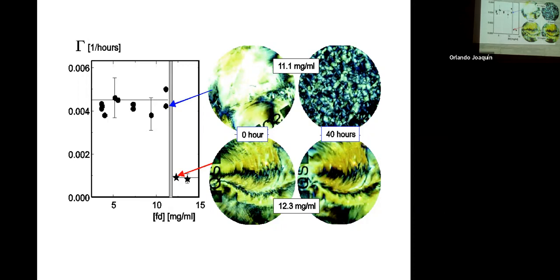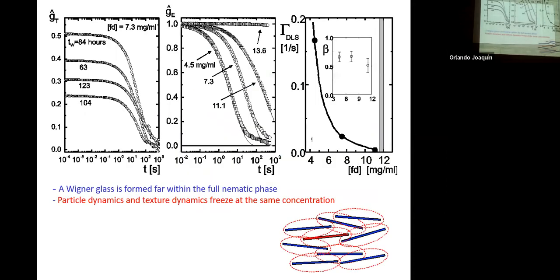Now to verify whether this is really a glass condition, we can do dynamic light scattering. So you measure the dynamics of single particles, the dynamics on the particle level. And there you also see that if you increase the concentration, this is also frozen. These are the decay rates here, but now obtained from dynamic light scattering - you look at the dynamics of single particles, on the second time scale. You see that the decay rate goes to zero at, within experimental error, exactly the same concentration.